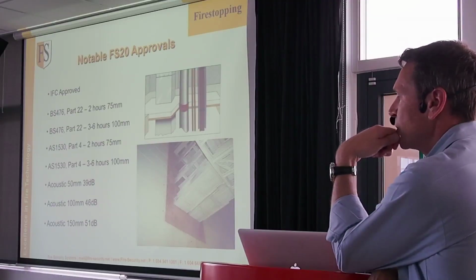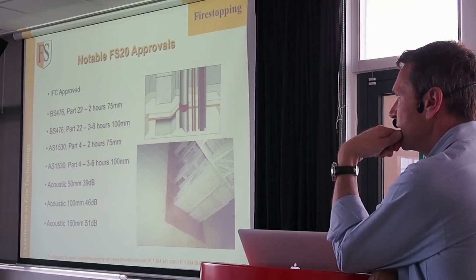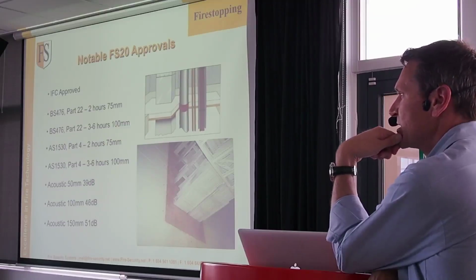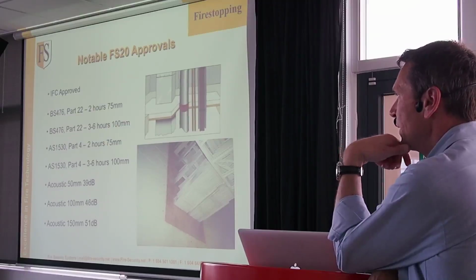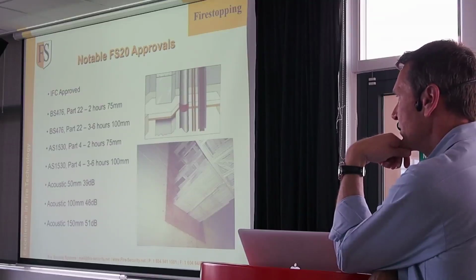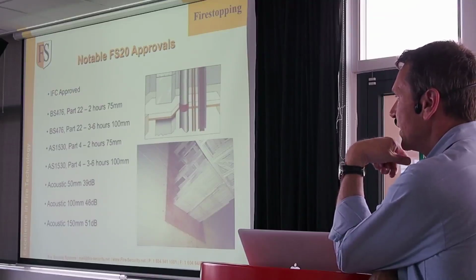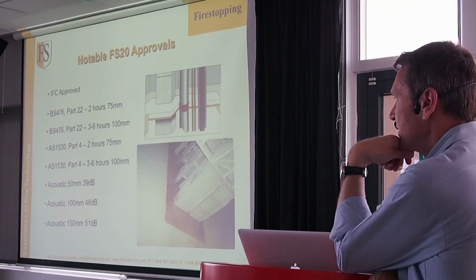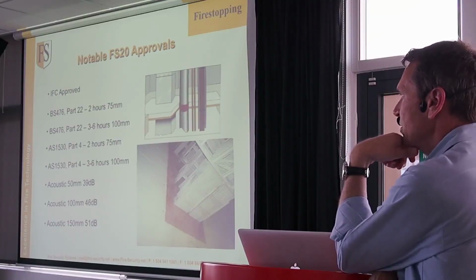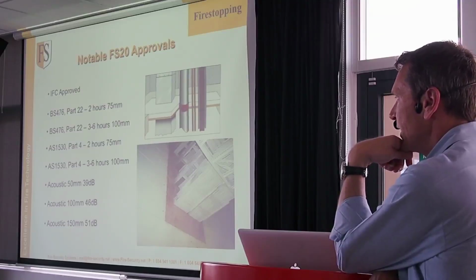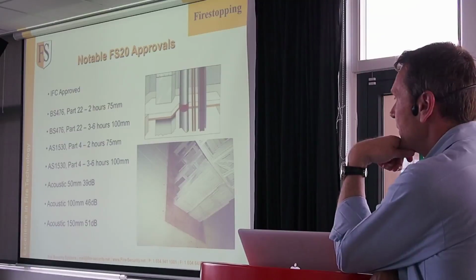So IFC approved. IFC is an engineering group in the UK. So British standard tested at Warrington, part 22, 2 hours, 3 and 6. Australian standards, part 4, 2 hours and 3 to 6 hours. And also at 100, you'll see an acoustic decibel rating here as well. So at 50 millimetres, we decrease 39 decibels, at 100, 46, and 150, 51 decibels.